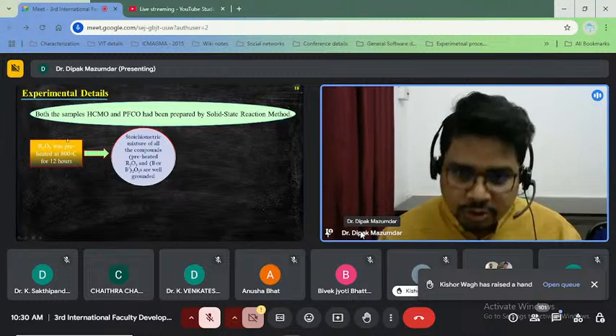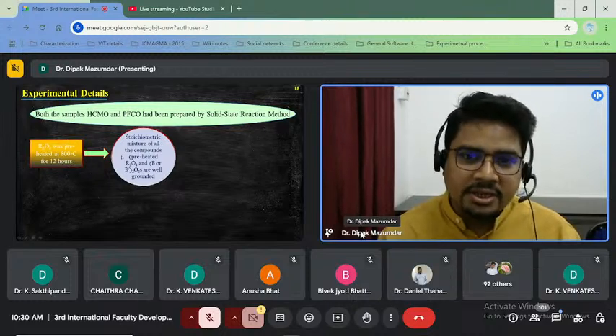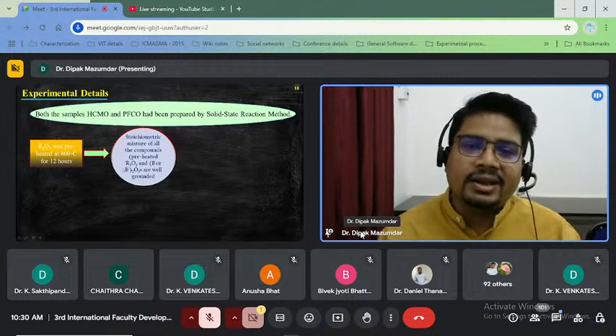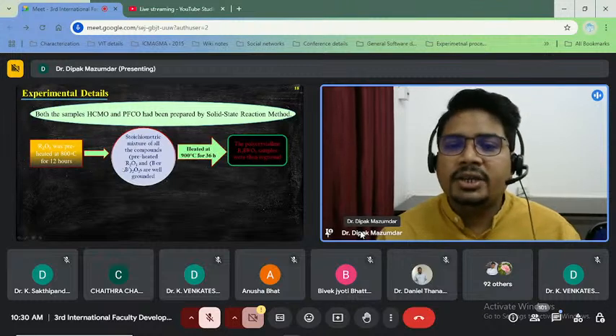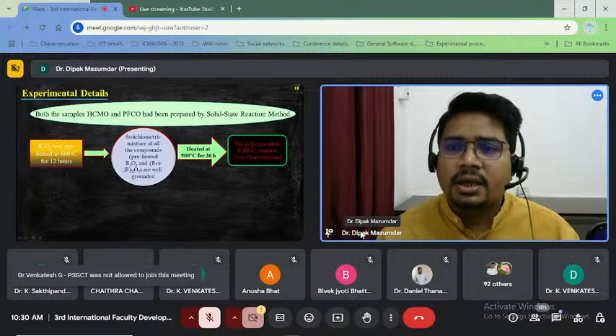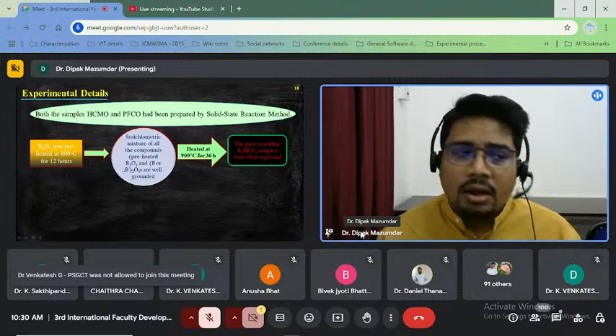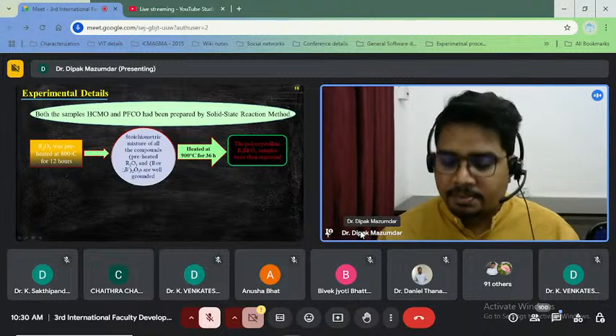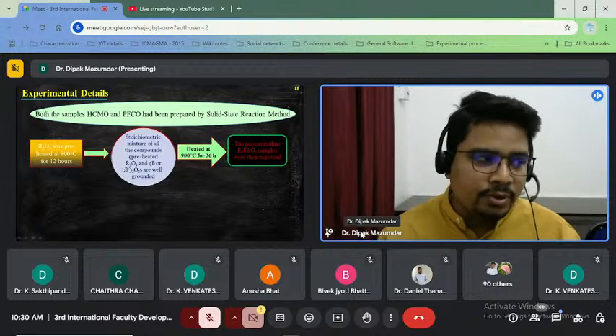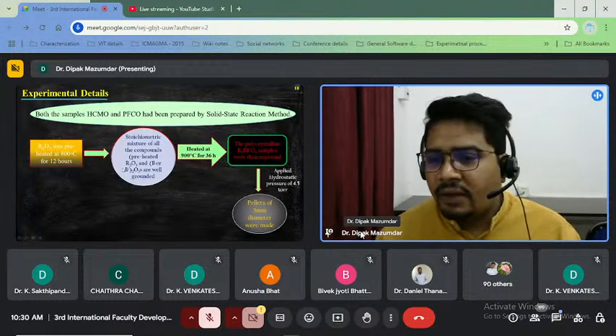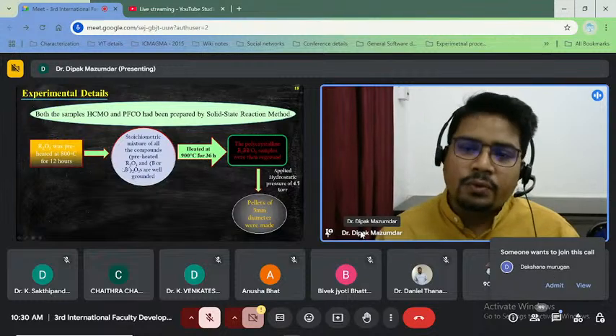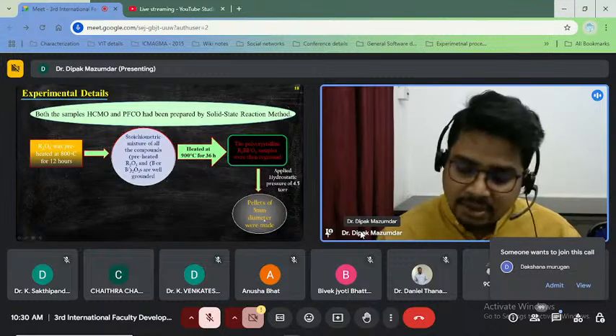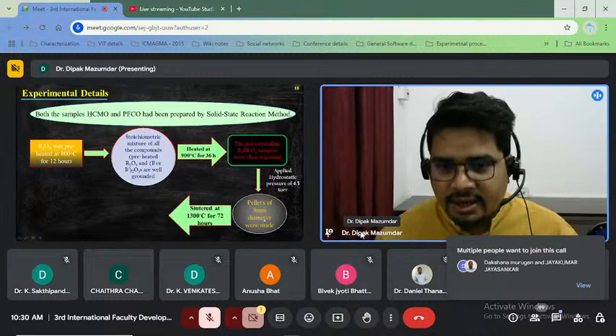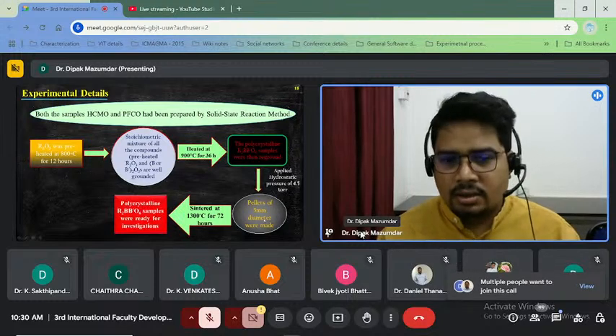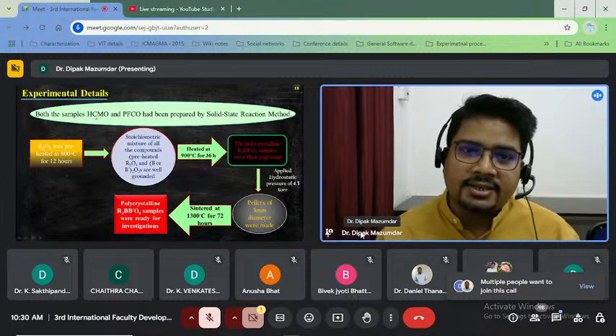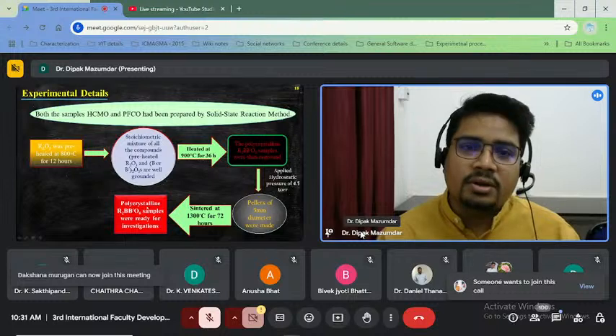Next, we take the stoichiometric mixture of the preheated rare earth oxide and transition metal oxides, and they are well ground in the presence of ethanol. Then we heated this at 900 degrees centigrade for 36 hours. As a result, we get a polycrystalline disordered form of this R2BB'O6 sample. Then we again regrind this, and after applying a hydrostatic pressure of 4.5 tons, we convert the powders into pellets of diameter 5 millimeters, and the pellets are further sintered at 1300 degrees centigrade for 72 hours, and we get our polycrystalline HCMO and PFCO compounds, which are now ready for investigation.